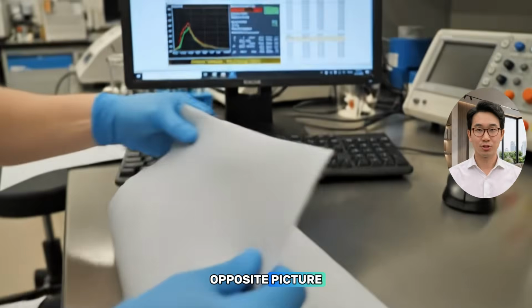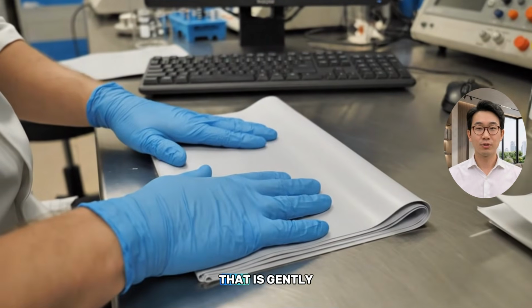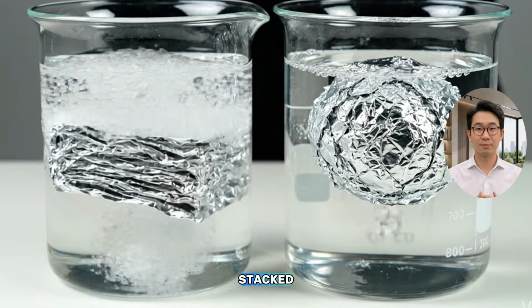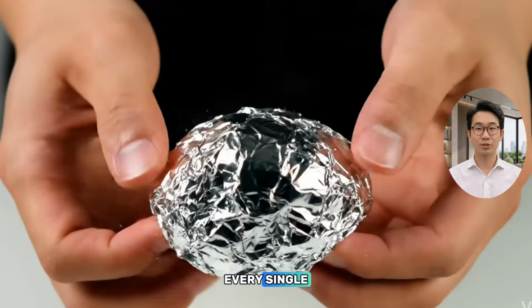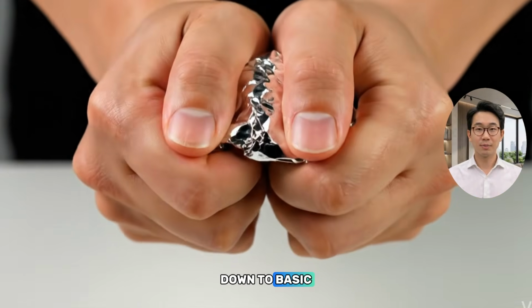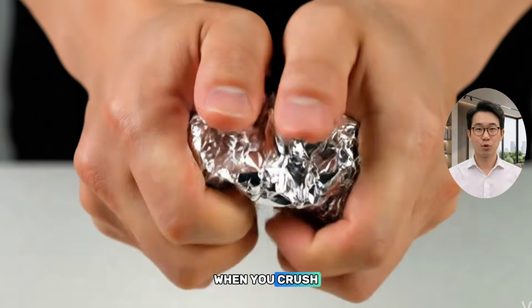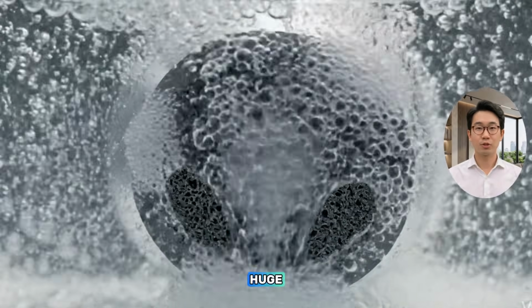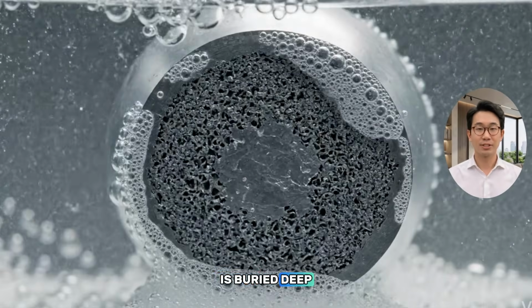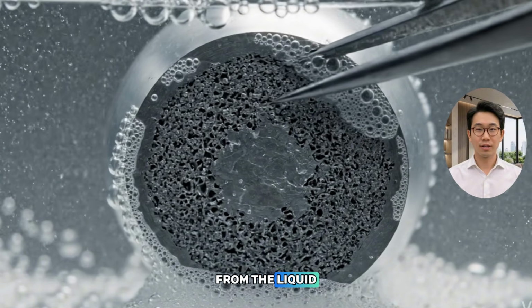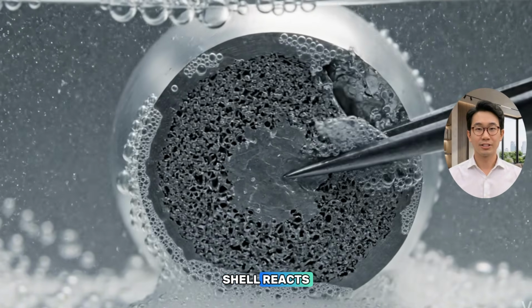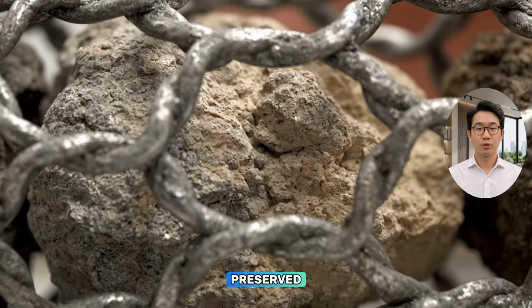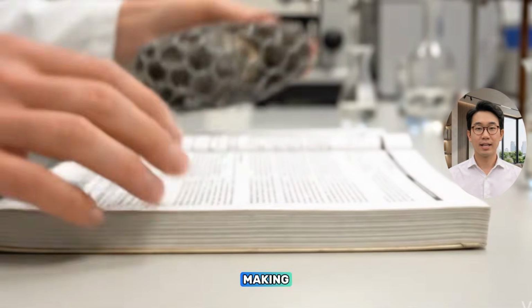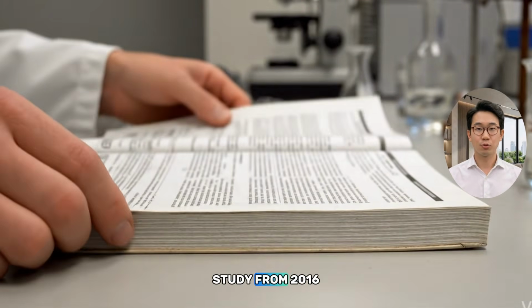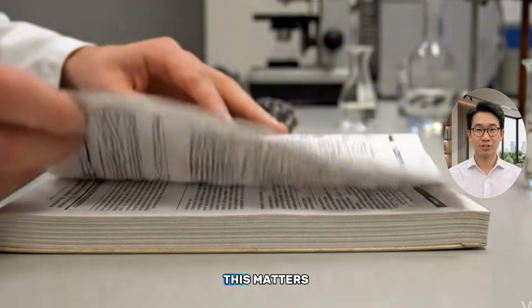But the hard data on hydrogen output paints a completely opposite picture. In rigorous testing, foil that is gently folded or loosely stacked beats a tightly compacted ball every single time. It all comes down to basic surface access. When you crush foil into a tight sphere, a huge percentage of the metal is buried deep inside, totally blocked off from the liquid. The outside shell reacts, but the core remains perfectly preserved, trapped inside a cage of its own making. A rigorous study from 2016 proved exactly how much this matters.